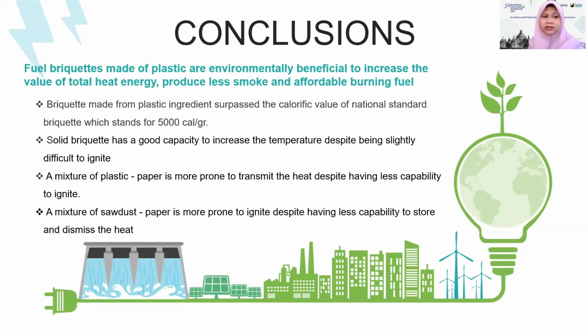So as the conclusion from this study, briquette made from the plastic ingredient has a calorific value greater than the national standard, which stands for 5,000 calor per gram. The water boiling test shows that this solid briquette has a good capacity to increase the temperature, despite being slightly difficult to ignite. The fuel briquettes made of plastic are environmentally beneficial to increase the value of the total heat energy, produce less smoke, and are an affordable burning fuel for the steam power plant.